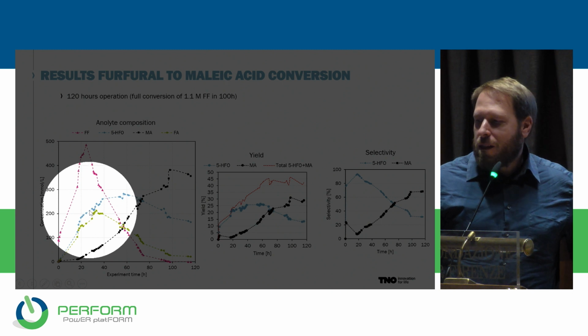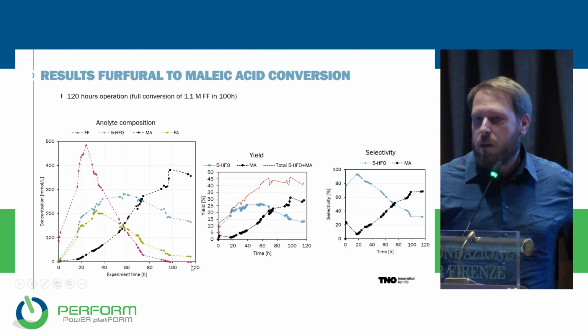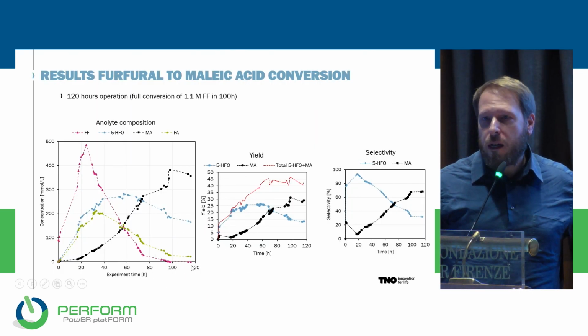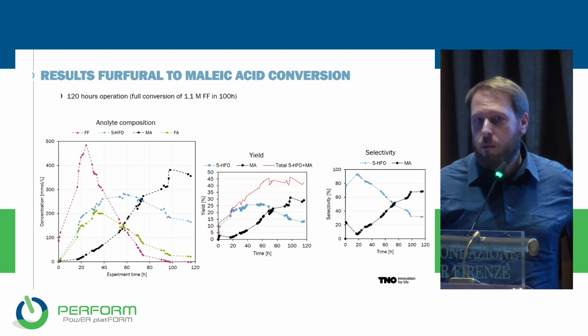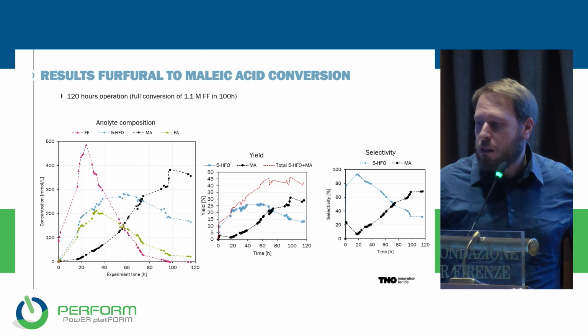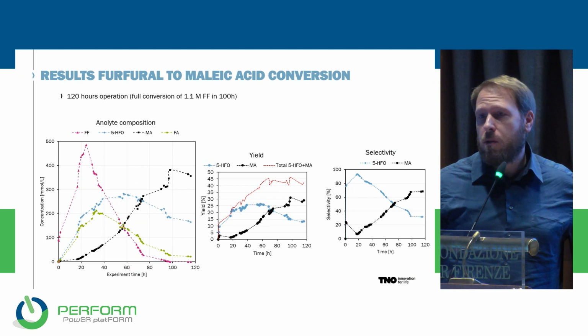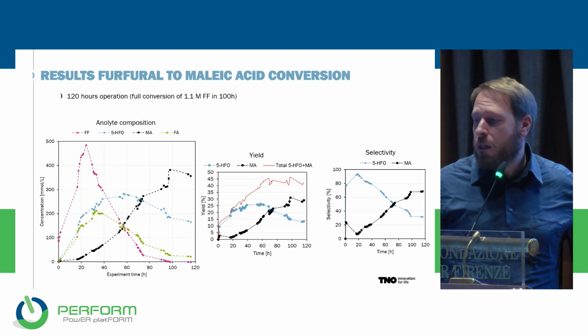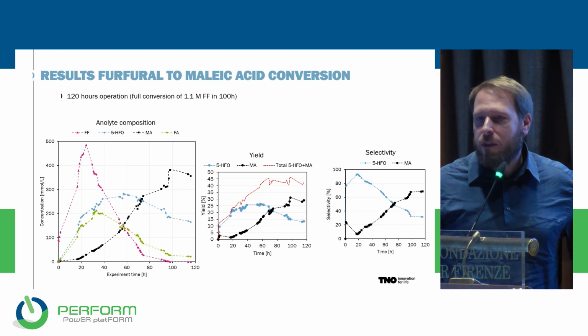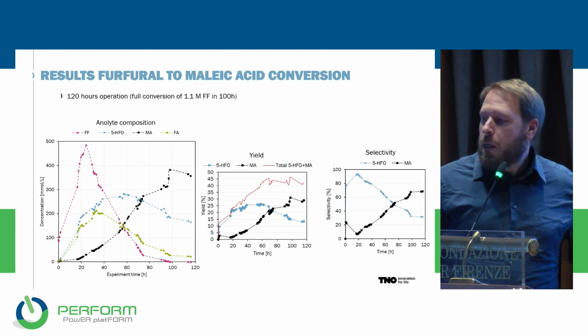But the puzzling thing is that formic acid is always difficult to recover, because you see that at some point the formic acid concentration goes down, and this is because you can oxidize formic acid to CO2. So you lose completely your formic acid in there. And this is also a problem because your Faraday efficiency is going to go down because you're using electrons to make something that is useless.